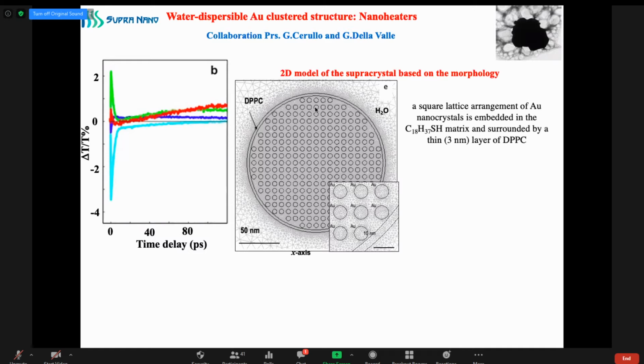You can see that the colloidosome has a very strong adhesion just at the edge, whereas the supraball doesn't have it. And similarly, they deform, highly deform. The colloidosome is able to deform, which is not the case for the supraball, because the supraball is an FCC supracrystal.